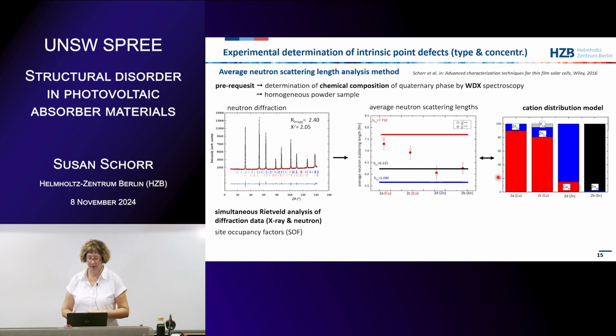So this is the cation distribution model which fits best to the experimental data. This gives the stars. The stars are the calculated average neutron scattering length. And this is the cation distribution model we made for this sample here. So we have zinc on copper antisites, copper on zinc antisites, zinc on tin antisites, and copper vacancies.